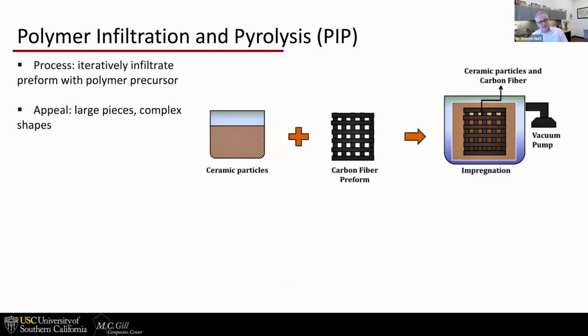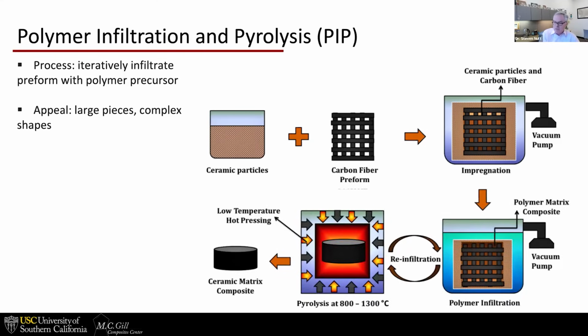PIP, polymer infiltration and pyrolysis. It's an iterative process. It's used for carbon-carbon composites, and has been for a long time. Basically you start with ceramic particles and a fiber preform, blend these things, impregnate with polymer resin mixed with ceramic particles, and then you pyrolyze to produce a CMC. Again, because it's iterative, it's slow, and there's closed porosity, upwards of 5% typically. Oftentimes, the number of PIP cycles used is anywhere from 3 to 6, and each cycle can take over a day. Figure it out. This is the process route that's used for the exhaust gas mixer.